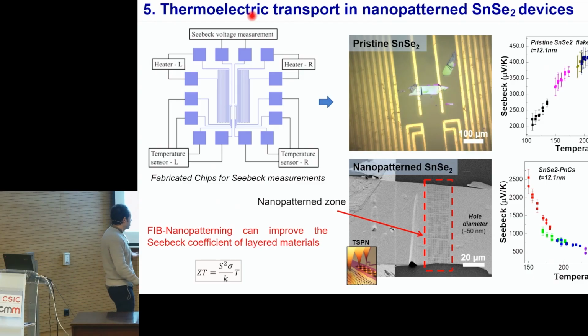One thing that we found that is interesting is that the nanopatterning that I showed you before also gives us very good results in the Seebeck measurements. We wanted to understand this because it's not straightforward. We know, as I showed you before, that with nanopatterning we can decrease the thermal conductivity of our material, and we can even guide the heat flow. But what about the Seebeck? Why would the Seebeck coefficient be increased when we create patterns in our material, when we create nanoporous membranes? Why would it be much higher? So we wanted to understand this.